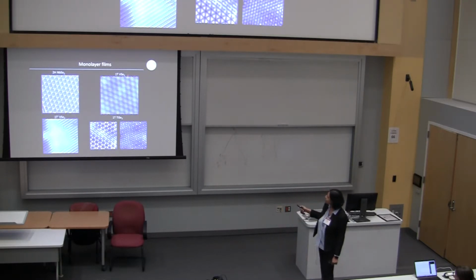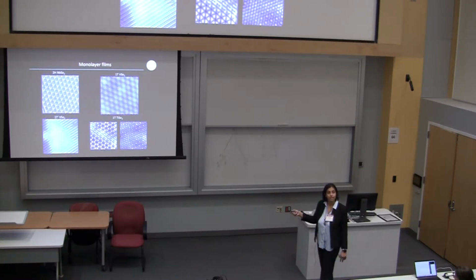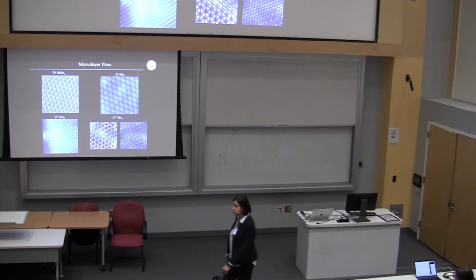And in fact, while playing around with it, we found we could grow both of these polymorphs depending upon the temperature. The nice thing about vanadium diselenide, which might also be a problem for magnetism, is the fact that even in the monolayer and bilayer limit, it has this really nice CDW pattern. You can see it as a pattern superimposed on the hexagonal arrangement of atoms. Does the lattice constant change much for the monolayers? No, it doesn't, and I'll come to that in a second.